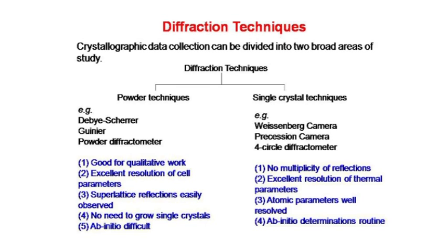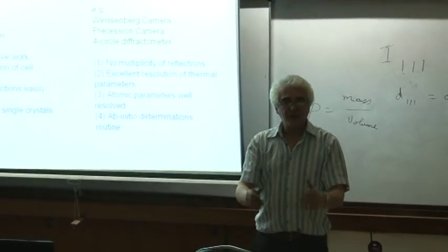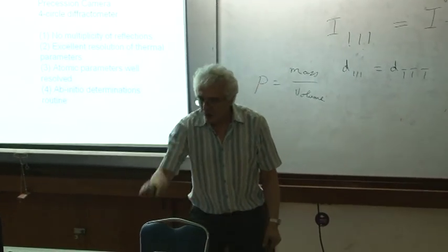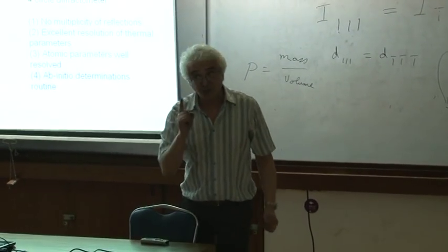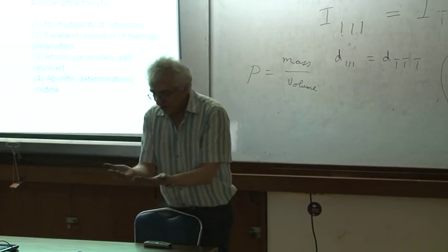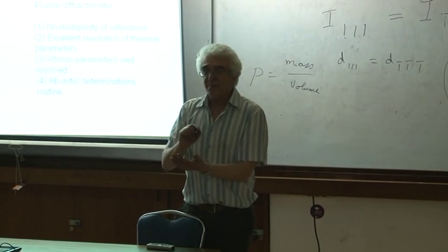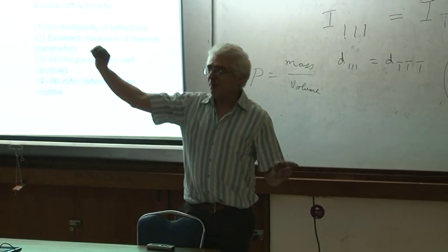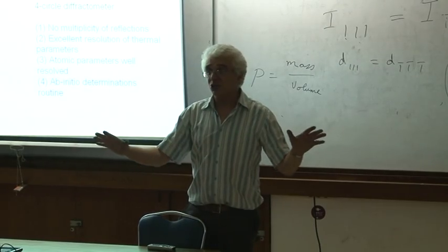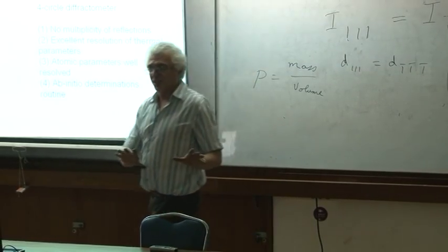What are the advantages? Well, powder diffraction is very good for qualitative work. If you want to know, has my reaction completed? Do I have the right stuff? Powder work is much better because you look at the whole sample. In single crystal analysis, you take 1 crystal, and of course you've got to take the best one. You're looking under the microscope, and you will find the very best crystal. But that might be the only crystal that is the compound that you are looking for, and the rest of it is rubbish. So it's not good for qualitative work.